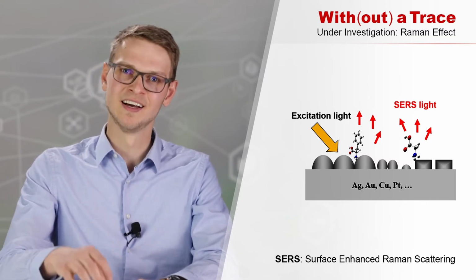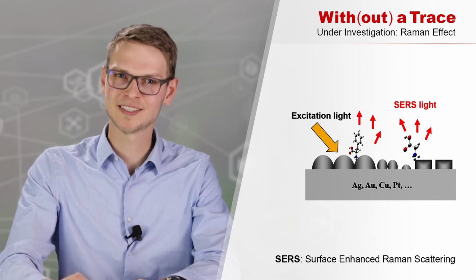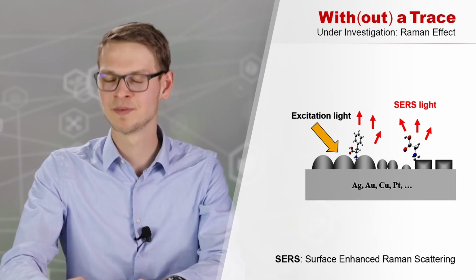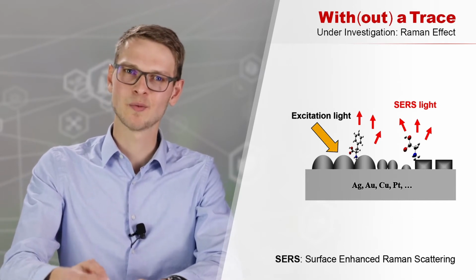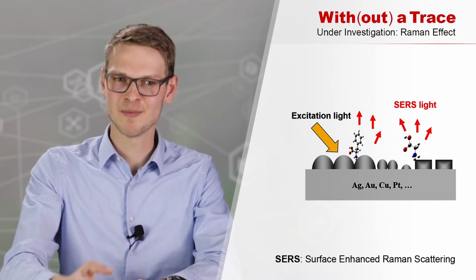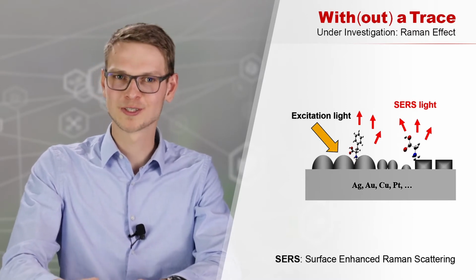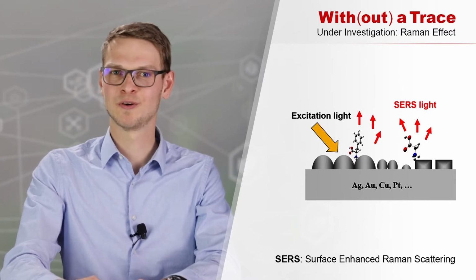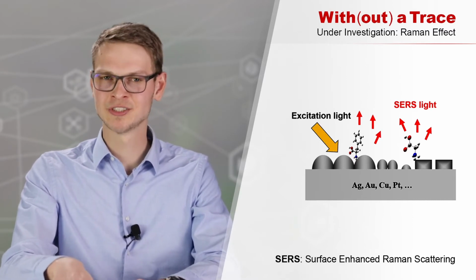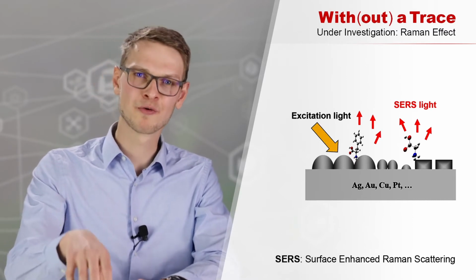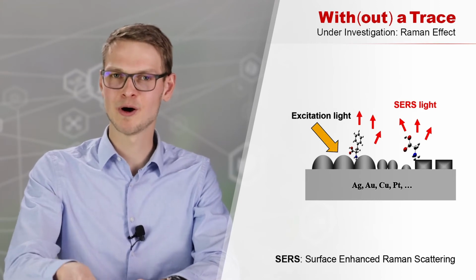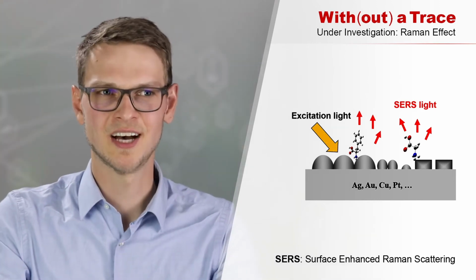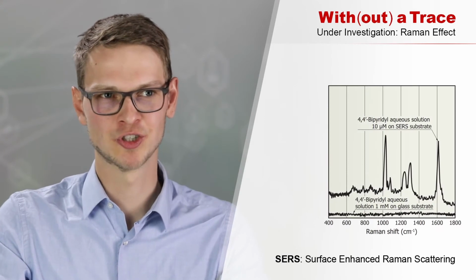And then a physical effect will take place, which is called plasmonic interaction. This will enhance the Raman signal by multiple orders of magnitude. So the range for this amplification is 10 to the power of 3 up to 10 to the power of 6. As an example, you can have a look at the chart shown.